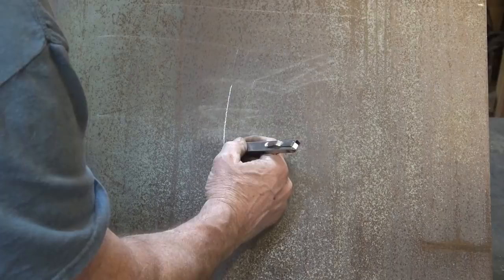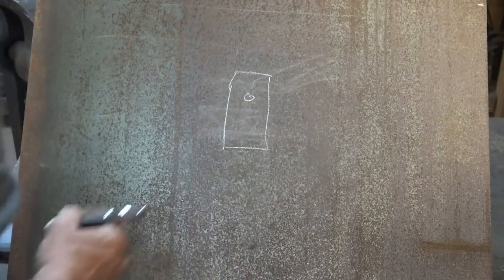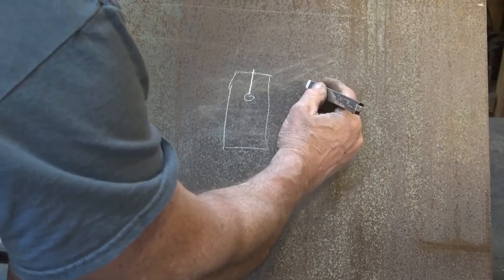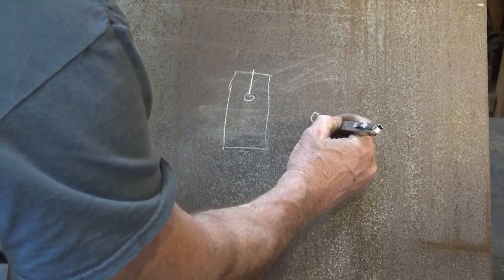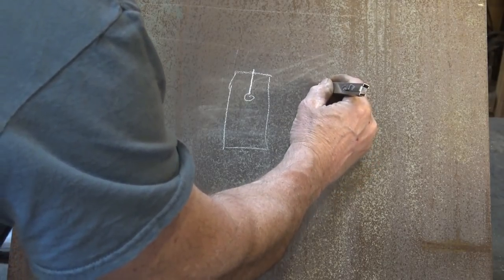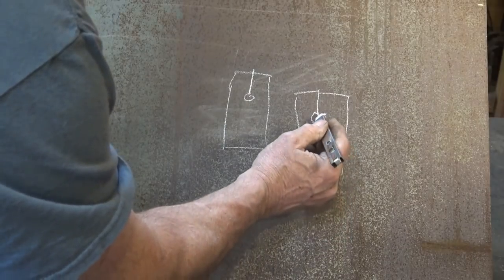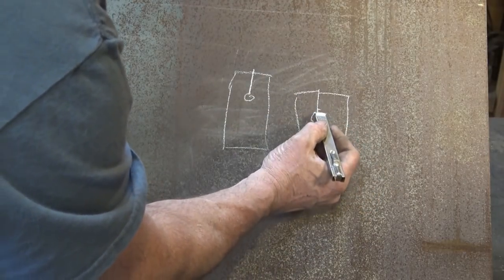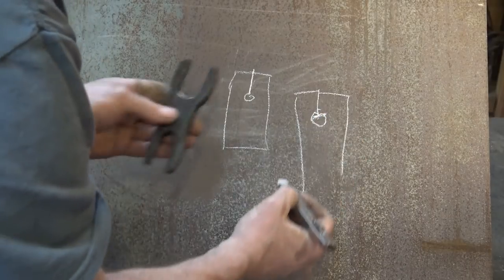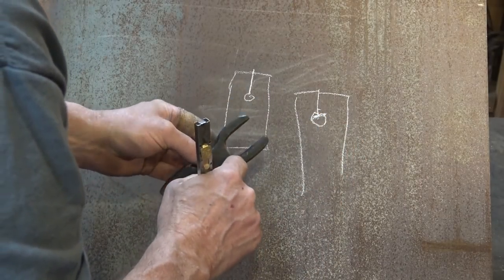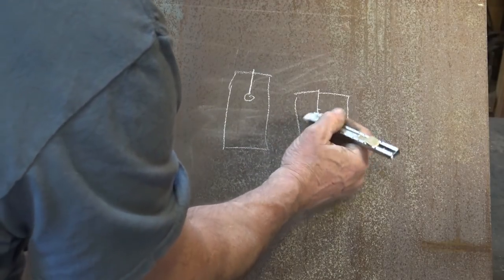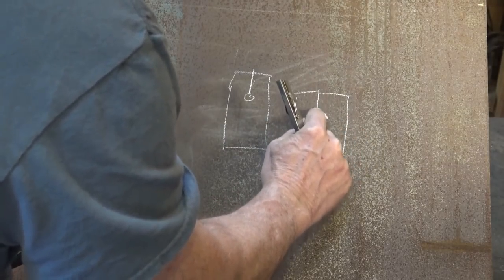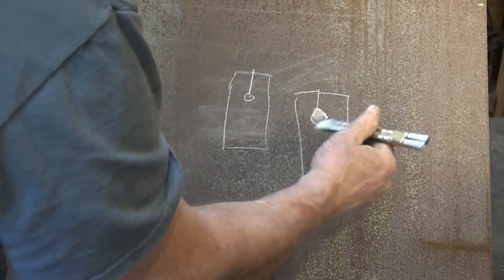When we made this bending fork, we started by punching a hole and then we chisel. Now as we chisel that hole, it starts to pooch into the hole kind of like this, and it leaves these little ears. When you forge these tines down and you're forging this way because you've opened it up, that can seal down. Again, if this is tool steel, that's where it's going to crack. For this tool, even in mild steel, that's likely to propagate a crack. So you don't want that in there. That's why I took time to file this off and make it look more like that before we did anything.